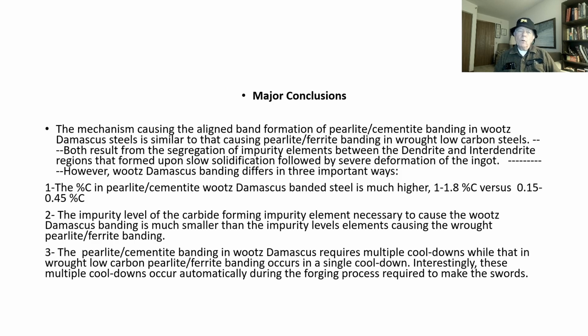However, the Wootz Damascus blades differ because they're higher in carbon, much higher, 1 to 1.8 versus 0.15. Second, the impurity level of the carbide impurity elements necessary to cause the Wootz banding is much smaller than the impurity elements causing the banding in low carbon steel. This guy is only 0.0089 or so, and this guy is 0.1 or so. The third one is that the pearlite cementite banding in Wootz Damascus blades requires multiple cooldowns, while that in the low carbon pearlite ferrite banding occurs on a single cooldown.